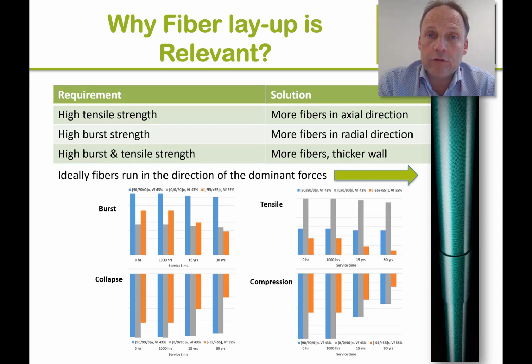If you look at the orange bars, the 55-55, you see that there's a much greater deterioration of performance in time, and that all has to do with the fact that these fibers are loaded in different directions than their actual orientation, which results in a lot of internal friction, internal stress in the pipe body. So the conclusion of this slide is, if you have a 0-90 layup with all the fibers in the radial and in the axial direction, you're going to get better performance with time than you would have if the fibers run in a different direction.